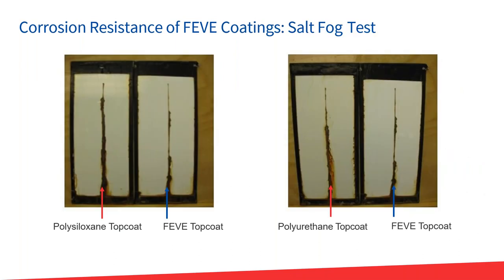In the paint world, we have some ugly tests, and these slides are not pretty, but they really show what goes on in a paint lab. You take these steel panels, you coat them, and you actually scribe the coating because you want to see the ability of the coating to protect from the corrosion spreading outside of that scribe. Here we're just trying to show that compared to the commonly used polyurethanes and polysiloxanes for corrosion-rich environments, the FEVE top coat performs the same, if not a little bit better.